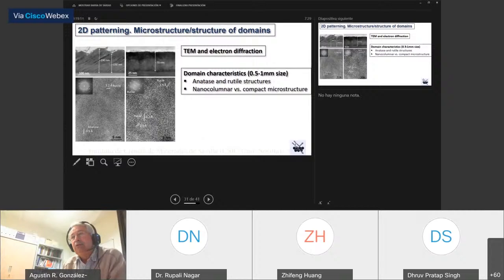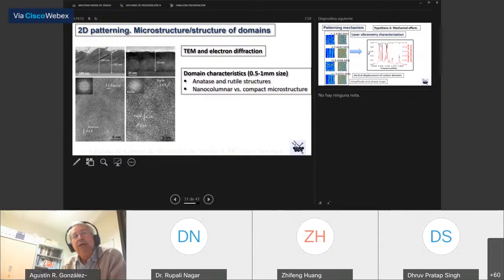Not only that is what happened. If we look at the crystallographic structure, this is a TEM analysis of these domains, the hill domains and the valley domains. You can see here that the hill domains are formed by the typical nanocolumnar structure of the titanium dioxide, while the valley domains correspond to a very compact, extremely compact titanium dioxide situation.